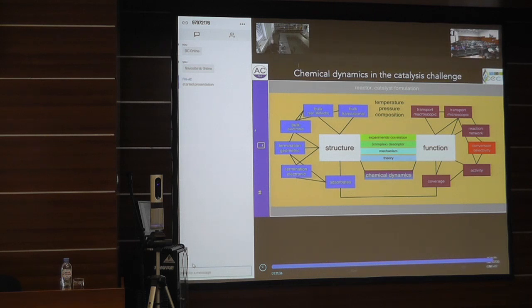And the real experimental parameter that links structure and function, which I hopefully have shown to you, is this phenomenon of chemical dynamics. Because the structure of the material is unfortunately controlled by the local chemical potential, and the local chemical potential is of course given by the function of the catalyst. And this gives a negative feedback loop, and this negative feedback loop couples the red parameters and the blue parameters in such a way that if you do not know this feedback loop, then you will never understand what the structure function relation actually is. That's the end of it.